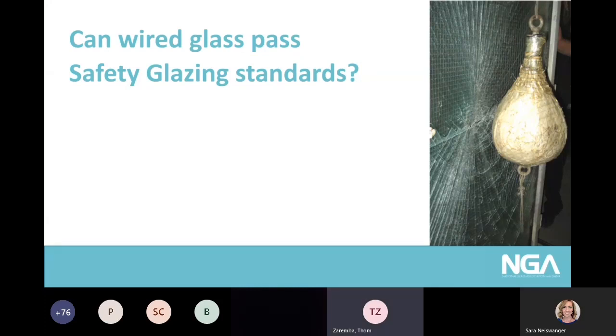Wired glass can be organically coated, and with that organic coating, just like a laminated glass or other forms of annealed glass or glass ceramics that have an organic coating to hold the pieces of the glass together after impact, with an organic coating, wire glass can be made to pass ANSI 18-inch, I'm not sure about 48, but certainly an 18-inch drop height test. Likewise, there are a number of organic coatings in the marketplace that will pass the fire test. Some will and some won't.